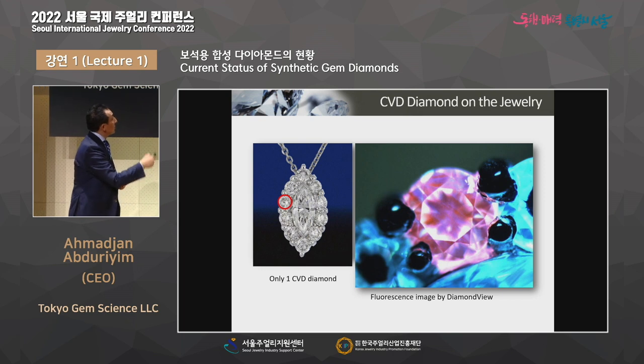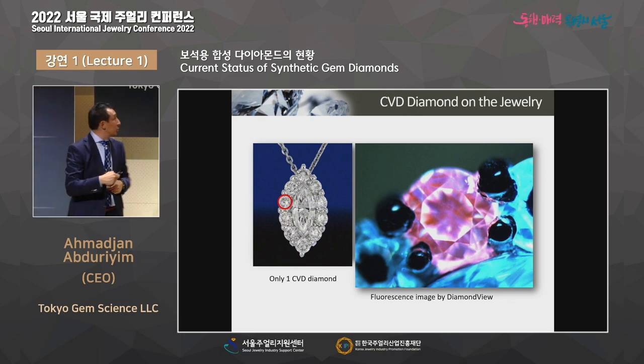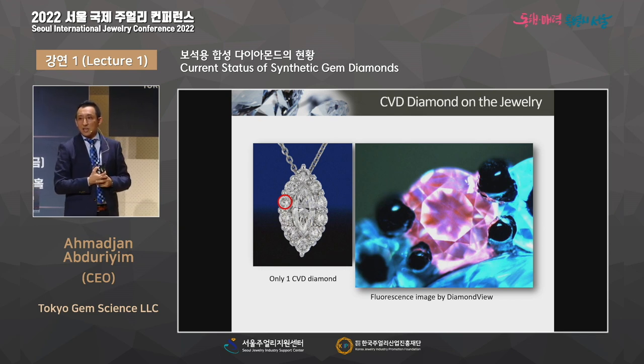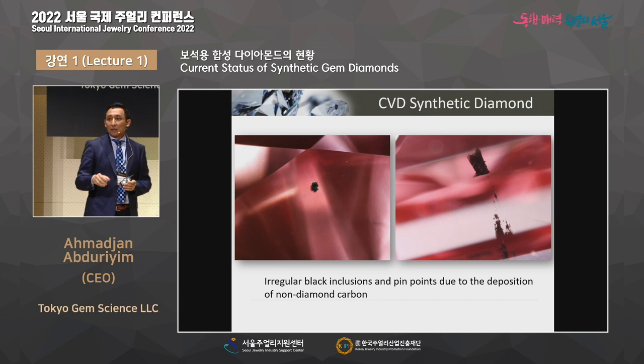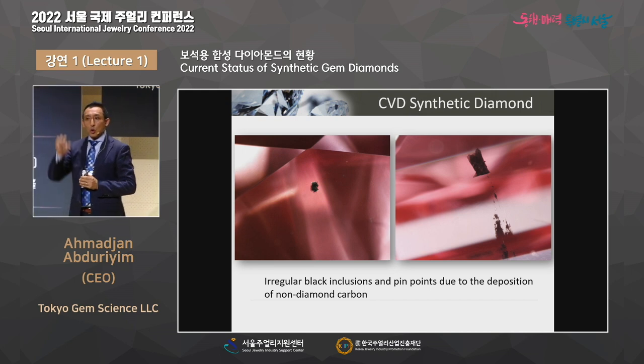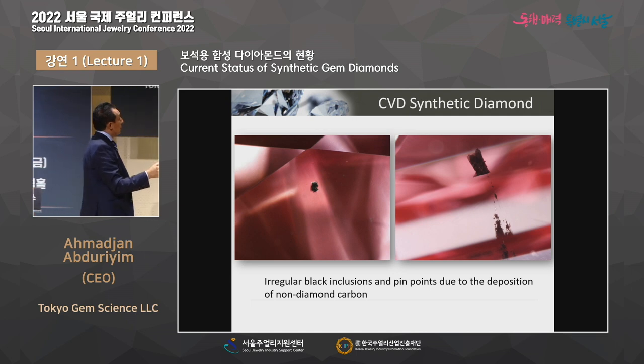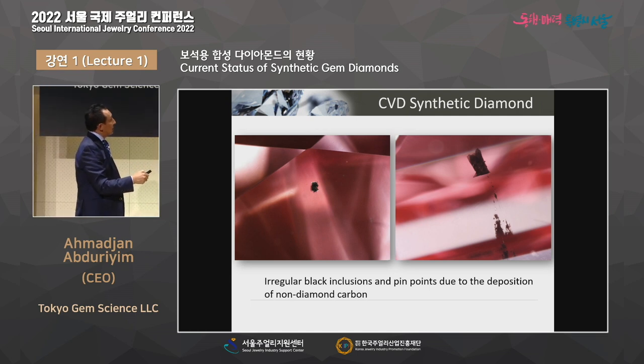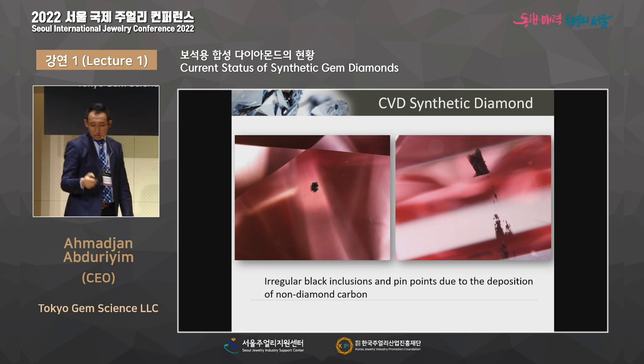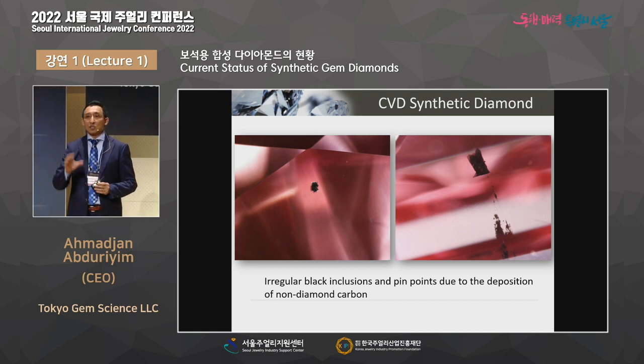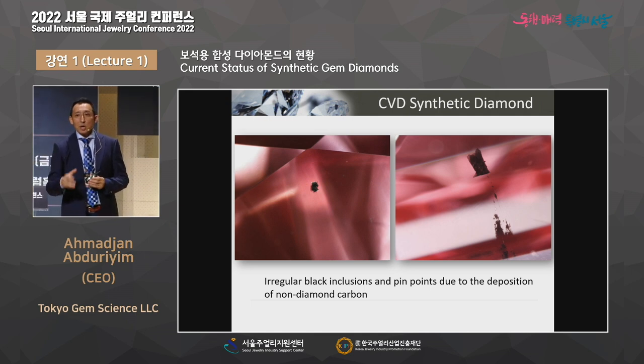This is one example: the jewelry also includes one piece of CVD diamond. Can you check that? No way. Even with the naked eye or a microscope, there is no way to tell. Normally, when you see a CVD diamond right after it is grown, you will see this kind of dark, graphite-like material. This is non-diamond carbon. It's not a diamond structure. So you can see pinpoints like this. This is the first production. However, when you look at an IF CVD diamond, you never find this kind of black inclusion.